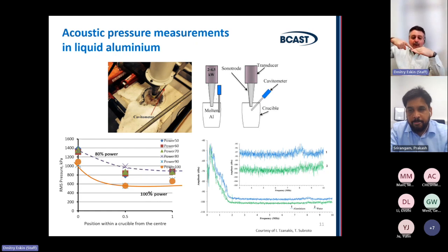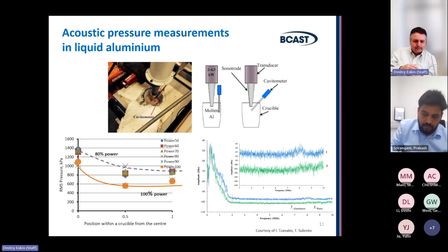Because in welding, for example, you can put a sonotrode following the pool. But in additive manufacturing, the speeds and the cooling rates are so high, so it's almost impossible to do. There are interesting approaches to that by introduction of cavitation through the pulsing laser, and that's maybe a way to do this, because you can induce cavitation by pulsing laser, and it is done in liquids like water. It's one of the means of studying cavitation. By pulsing, you can concentrate your energy in a certain point and create cavitation there.